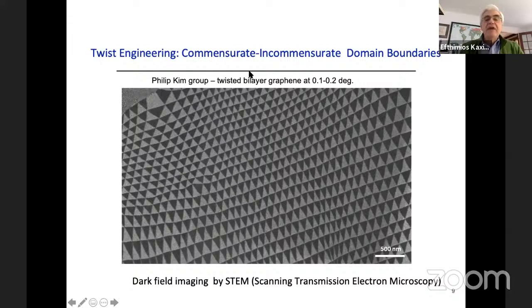So this is graphene on graphene, two layers, and the twist is about 0.1 to 0.2 degrees, and you see this pattern, which means that the actual structure of the two layers has changed. It has adjusted to the twisted stacking and produced this pattern of atomic positions. So these are not atoms that you see, these are large areas. But the underlying atomic rearrangement produces this pattern that I'm showing you. Okay, so the question is, what are the implications of this?